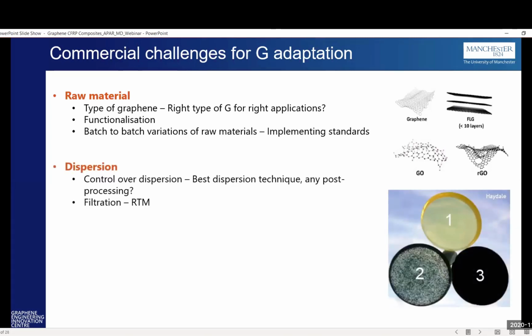Of course, the second is the dispersion, how well the graphene is actually dispersed in the matrix, and what are the best dispersion techniques that you have to use. Say, for example, do you have to use a high shear method or a low shear method, or do we have to implement any post-processing techniques in order to have the dispersion in the final product? Some may ask whether, in the resin transfer molding procedure, filtration could be a problem. And there are techniques currently implemented to avoid this filtration of graphene nanoparticles too.